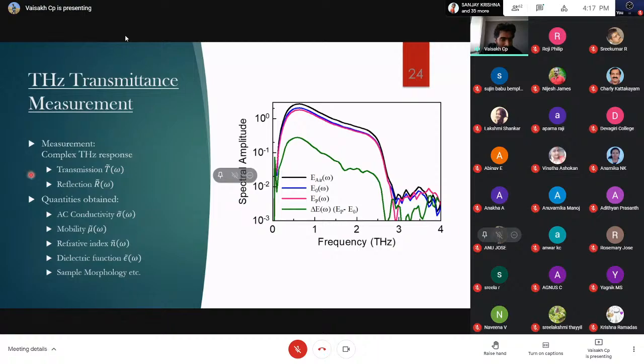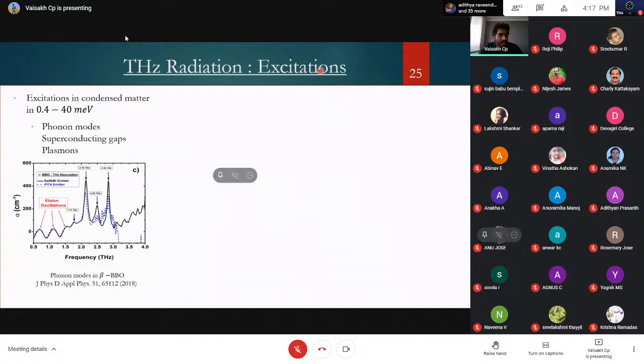measuring the transmission T of omega, or in the reflection mode, one could arrive at the AC conductivity. So you get the sigma of omega of the material, mobility, refractive index, dielectric constant, and one could find out all these parameters about a material. The question is why, and what information are we looking at by studying such materials.